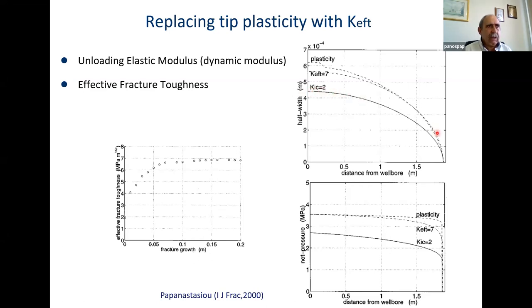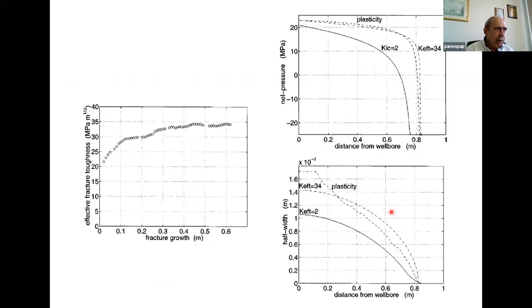So this is with elasticity with effective fracture toughness, and with full plasticity. You can see here that the effective fracture toughness prediction is close to plasticity, and the same result we can get with the pressure profiles. The pressure profile predicted by the effective fracture toughness is quite close to plasticity. And I have another example where the effective fracture toughness this time was 34.